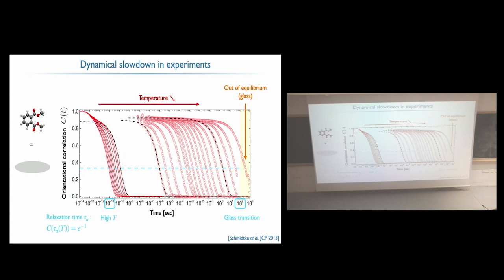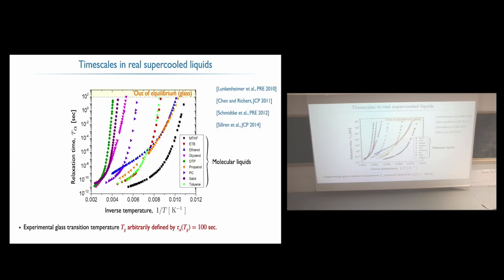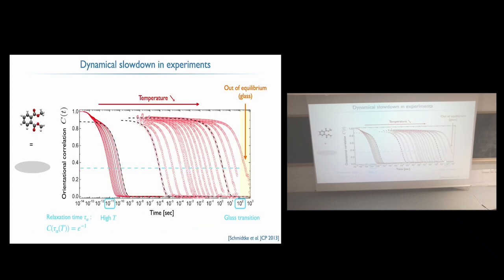And if you want to sample supercooled liquid, so something that's in equilibrium, that's not a glass, you want to make sure that from the beginning to the end, you really have sampled new configurations. So you want this quantity to have completely decorrelated. So this is actually something that defines the glass transition, in an arbitrary way. So when the relaxation time is too long, then you're out of equilibrium and you transform into a glass.